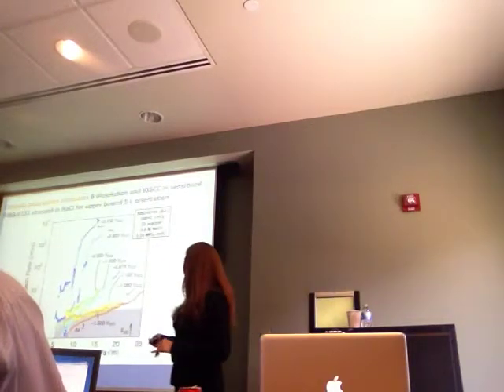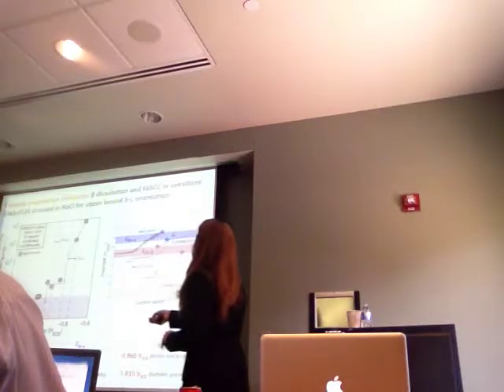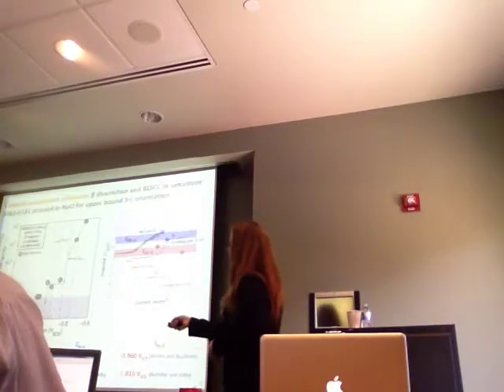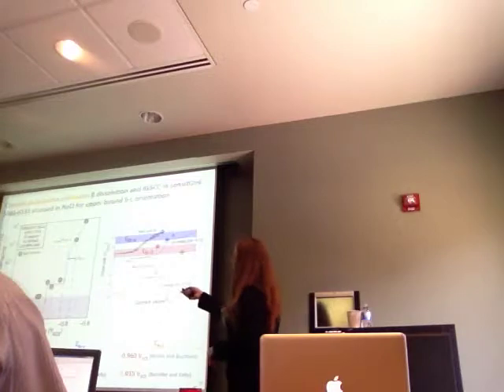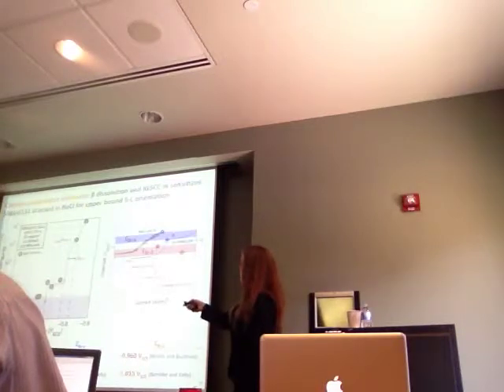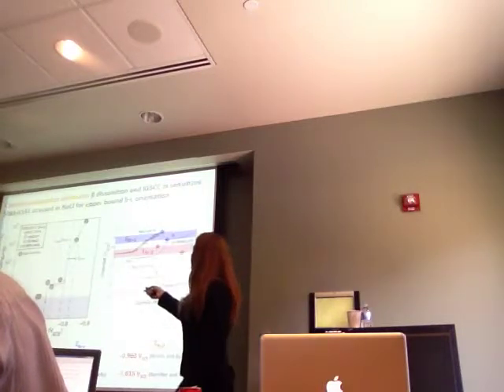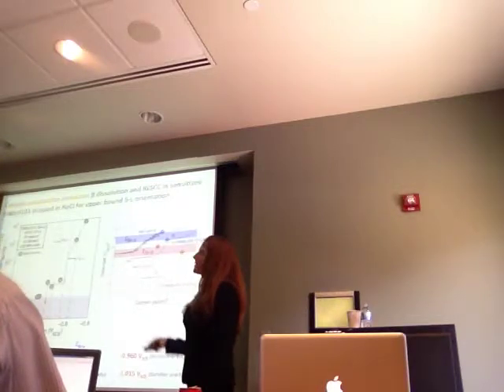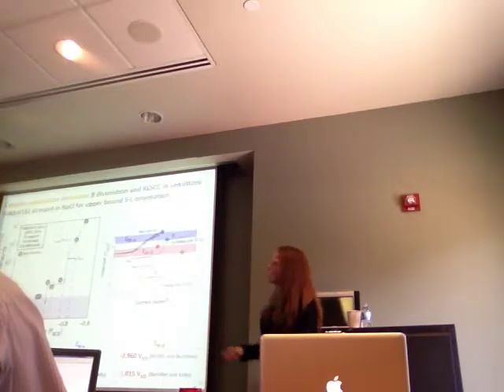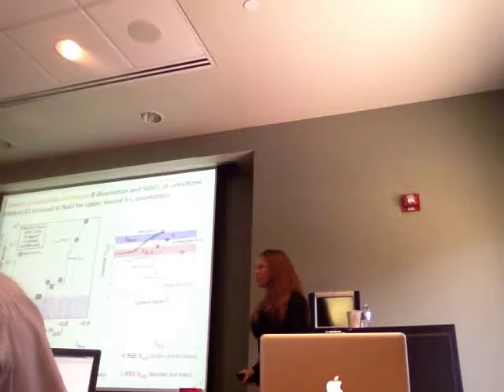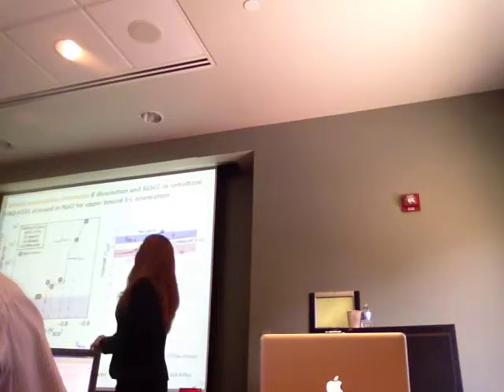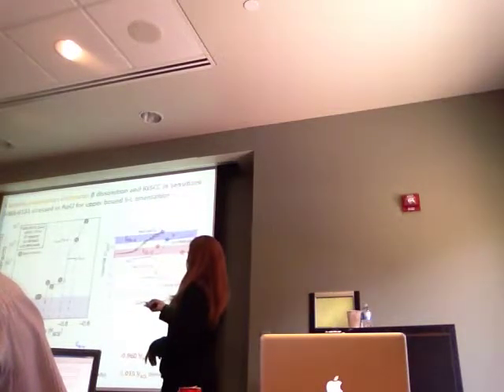And a better way to look at this is with this plot here. I have your crack growth rate versus your applied polarization. And you can see at the very high potentials, you have very fast crack growth rates. You drop significantly to this region of potentials here, and then you drop to the resolution limit once you're below that potential.